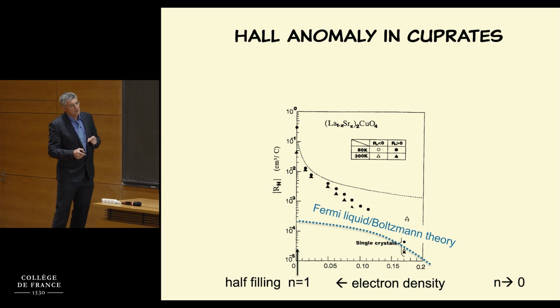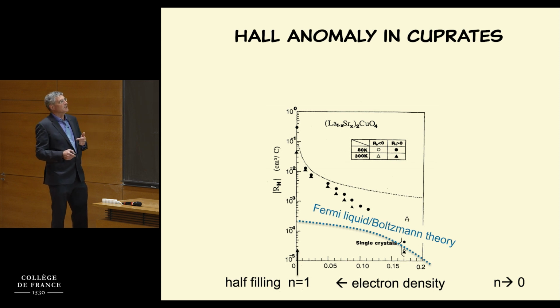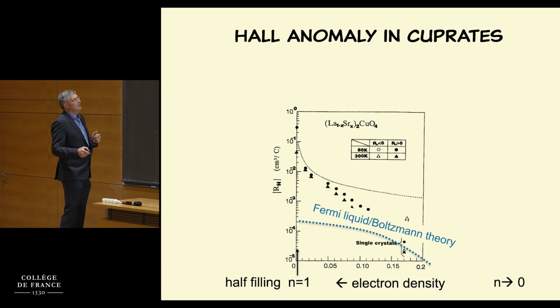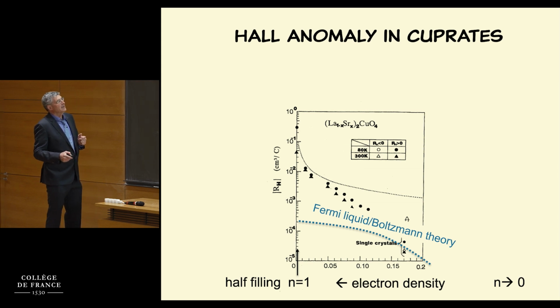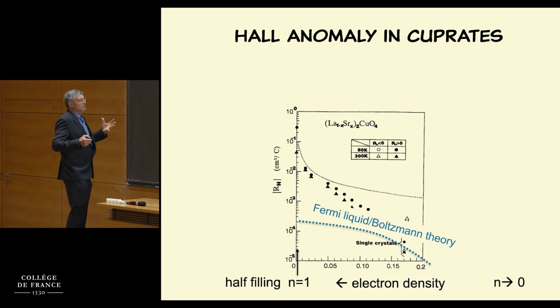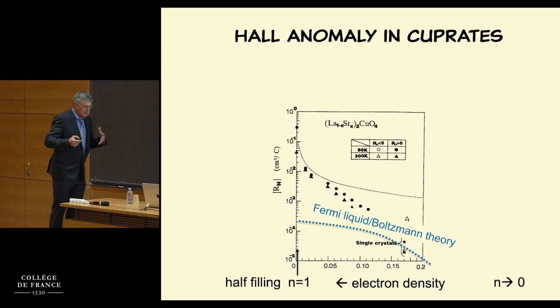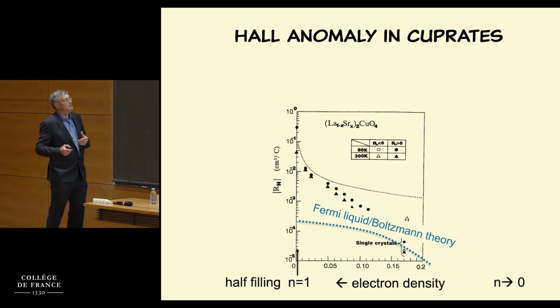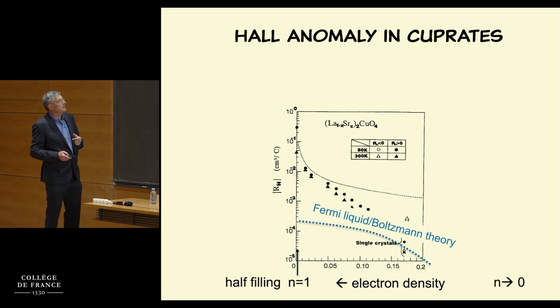Now, the fact that it's positive, one argued, comes from adding next nearest neighbor interactions, pushing the zero crossing to some value. So getting a positive number here is not necessarily a sign of breakdown of Fermi liquid theory, but the fact that it's divergent, and this is at quite high temperature, above any kind of disordering transition or breaking of symmetries due to lower energy phases, is an anomaly. This is something that we need to explain.